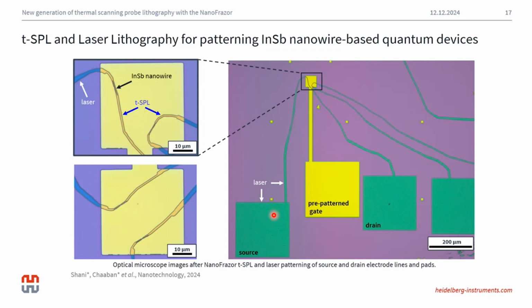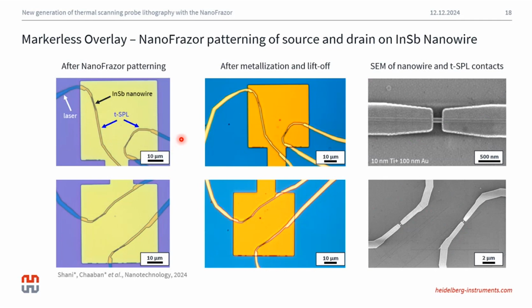This was a collaboration we did with the University of Minnesota, who supplied us with the nanowires. And we performed the patterning and the pattern transfer. You can see a side-by-side view of how this looks after metallization and liftoff. And finally, the final SEM images of the fine contacts overlaid onto the nanowire. If you look closely, you'll notice that these contacts that were written with the NanoFrazor have near perfect alignment to the nanowire. And in this case, we achieved a gap of around 200 nanometers contact to contact. This is quite impressive if you consider the large amount of metal which was deposited, in this case, 110 nanometers of metal.